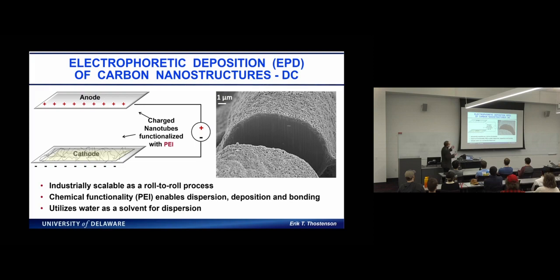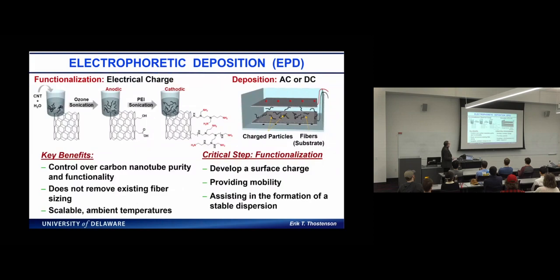Those are the carbon nanotubes, and the chemistry sticks, it bonds to the surface of the fiber, for different chemistries, but the nanotubes also bond because they also react together. So we have a very, very uniform and well-bonded structure on the surface of the coating. This is just a quick highlight that we have a lot of control over the nanotube purity and functionality. We're doing this at ambient temperatures.